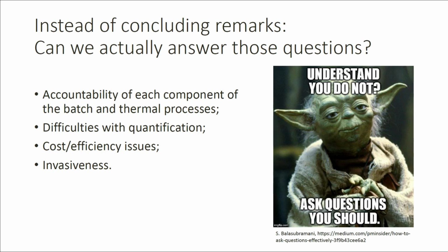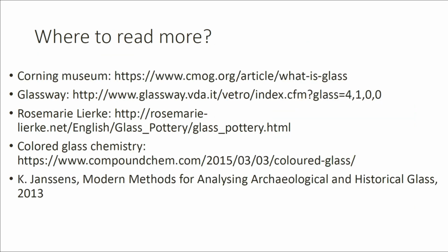If you think that if you got some number and you can believe it, you will very soon find yourself in a difficult situation. Glasses mostly consist of relatively light elements that are not always detectable and or quantifiable with conventional methods. If you want a clearer picture, the invasiveness is inevitable, and this is not a great news for cultural heritage objects. The study might be too costly or the outcome is not even worth publishing. In any case, one must study the object as a whole and try to explain all the features of material to the best of his or her knowledge.